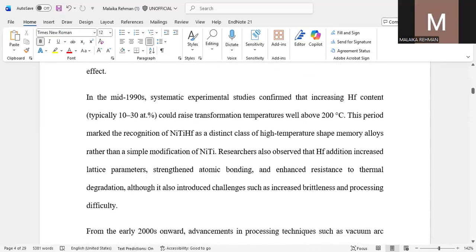Then, in the mid-1990s, systematic experimental studies confirmed that increasing hafnium content, typically about 10 to 30 atomic percent, could raise transformation temperature well above 200 degrees Celsius. This period marked the recognition of nickel titanium hafnium as a distinct class of high temperature shape memory alloys, rather than a simple modification of nickel titanium. Researchers also observed that hafnium addition increased lattice parameters, strengthened the atomic bonding, and enhanced the resistance to thermal degradation, although it introduced challenges such as increased brittleness and processing difficulties.